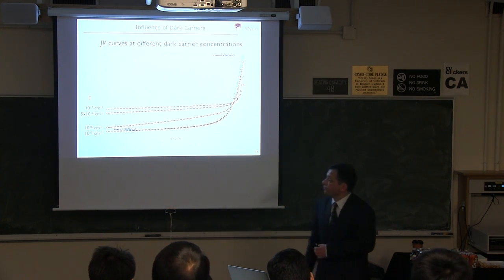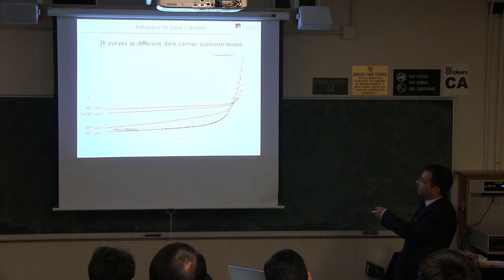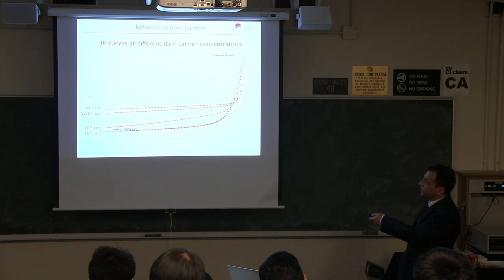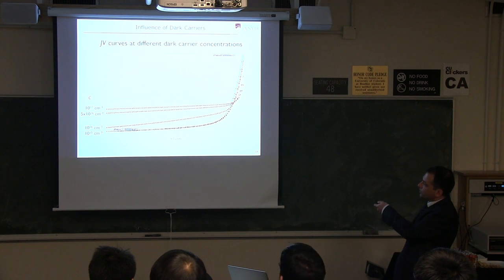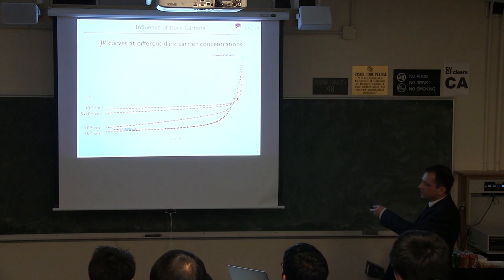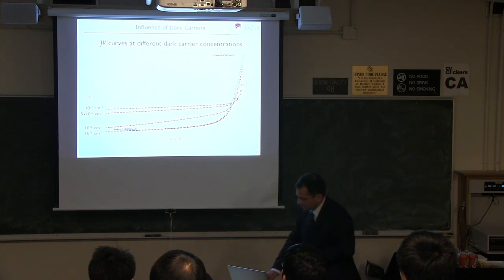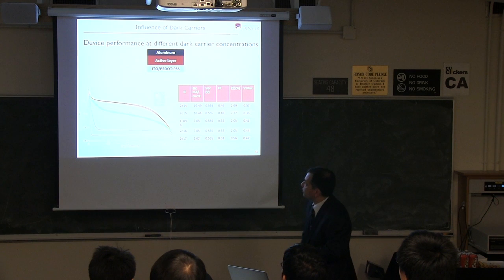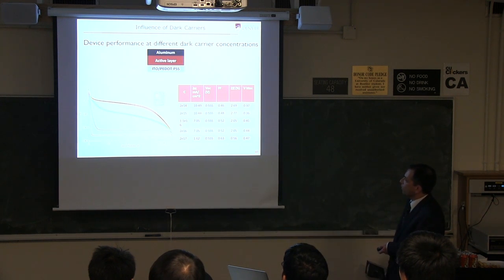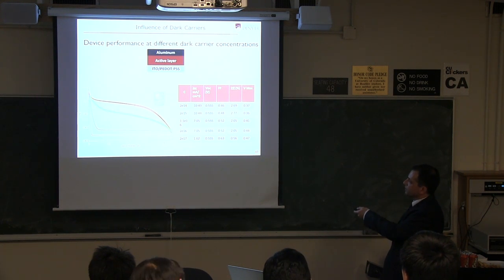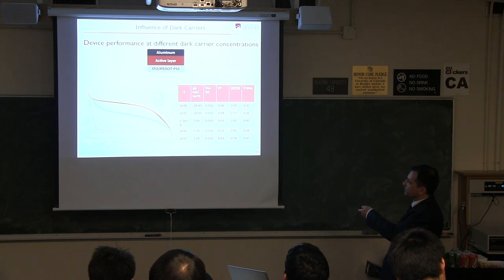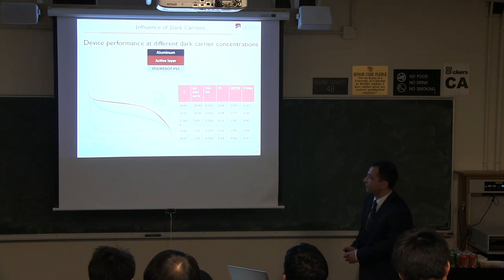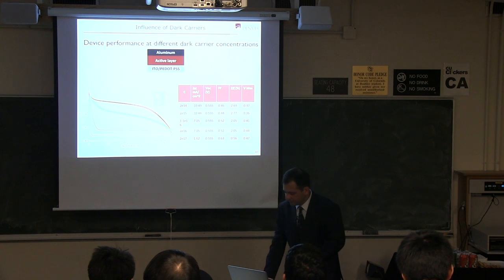And by the way, if you look at the impact of the carriers on the JV curve, at about 10^16 is when you start to see a loss due to recombination in that dead zone of the device. And at 10^17, you start really killing the device. Just to put some numbers on it, if you take a device that works at a nominal 2.7%, 3%, and you've got low dark carriers, if you bring that up to 2×10^16, you're down to 2%, and at 2×10^17, you're at about 0.5%. So we definitely want to get rid of those carriers.